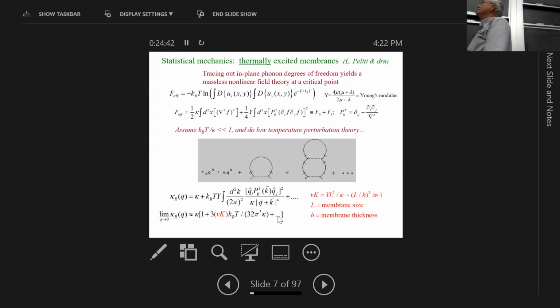So the renormalized bending rigidity, as a function of some external wave vector, is the bare value. Then you get something proportional to temperature. It's a kind of low temperature perturbation theory we're doing here. And when you evaluate this little Feynman diagram, it's the same as this one here, symbolically, you find a correction to the bending rigidity. And it looks a priori good because you get a ratio of kBT over the bending rigidity. That's dimensionless. It's typically like 1/50 in many systems. There's a 32 pi cubed in the denominator. That's great. But then there's an infrared divergence in this integral that produces, as a prefactor, the Foeppl-von Karman number, which even if this is small, could well be 1,000,000 or 10 to the 12th for graphene. So it's an explosion of positive renormalization of the bending rigidity.